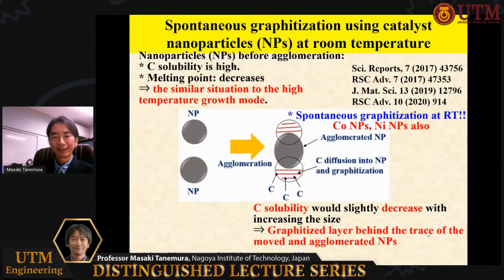Back to the nanoparticles. Generally, for nanoparticles, the carbon solubility tends to increase because a larger fraction of carbon atoms is expected at the surface, the surface-to-volume ratio is larger, and the melting point decreases. These situations are similar to the catalyst surface at high temperature.